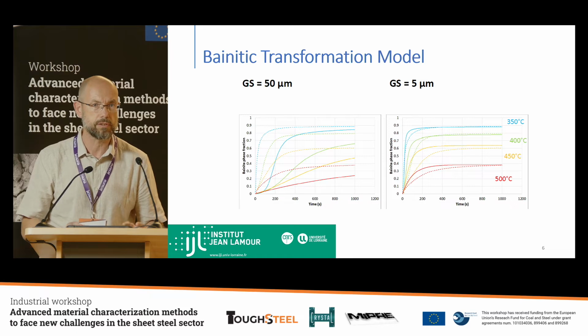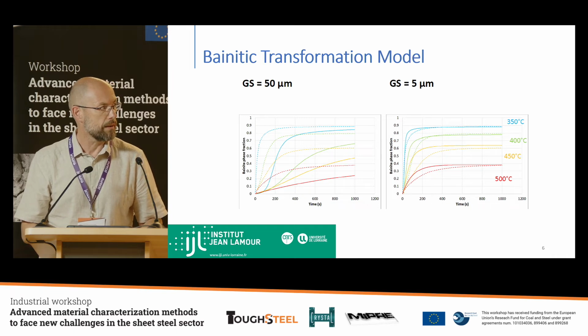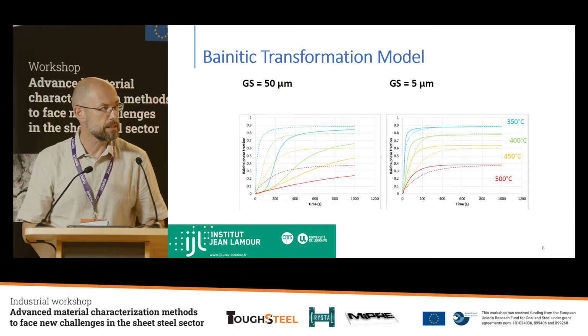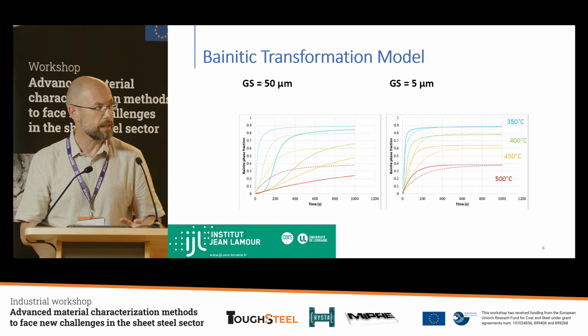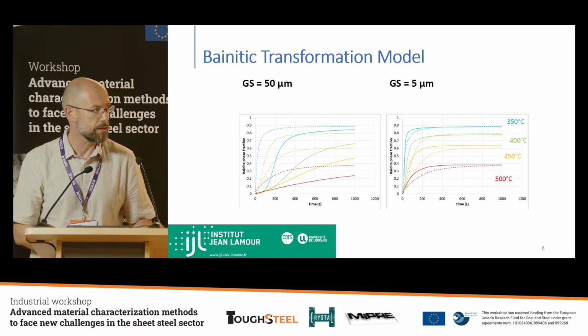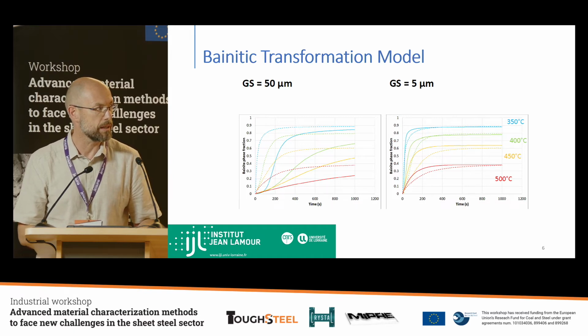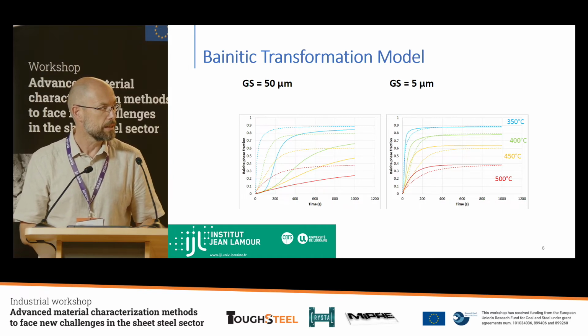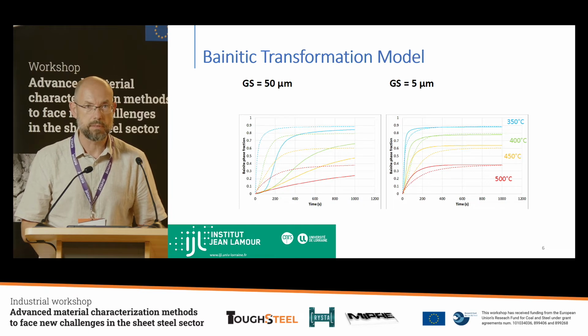This type of transformation is quite complicated in order to introduce this type of effects. The solid lines are the lines predicted by the model. The dashed lines are the actual experimental values that we obtained in the project. Of course, there is room for improvement, but the direction is quite good.